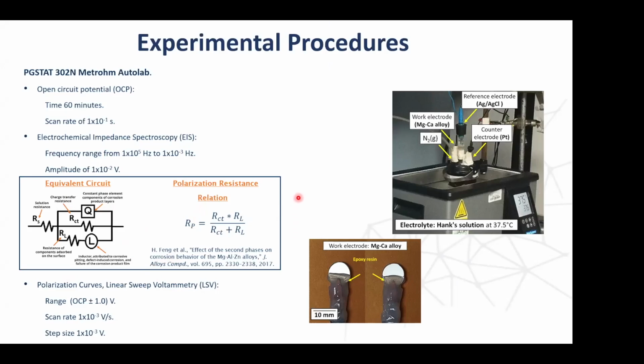So we process the HPT magnesium calcium alloys. We prepare the surface. We usually have to go fast because oxidation is quick in these materials. We protect the connection with epoxy resin, and we make a connection to the electrolyte, so that we can expose the bulk ultrafine-grained